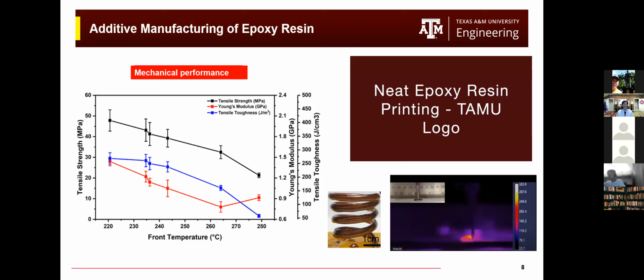So in your frontal curing method, do you see a difference in physical properties compared to traditional methods, or no difference? Yes. So as I understand, the tensile strength is affected by a lot of factors, but solely from our experiment, what I observed is that the frontal curing method has comparable tensile strength to traditional ones. Although the molding process right now is more for parts with fewer defects, because our process is still in its prototype stage, in terms of the material property between these two methods, I don't see much difference in the experiment.